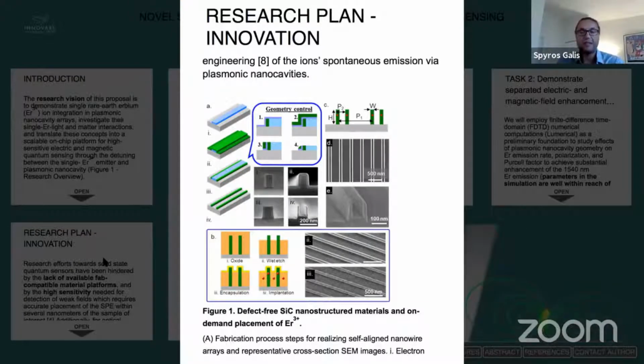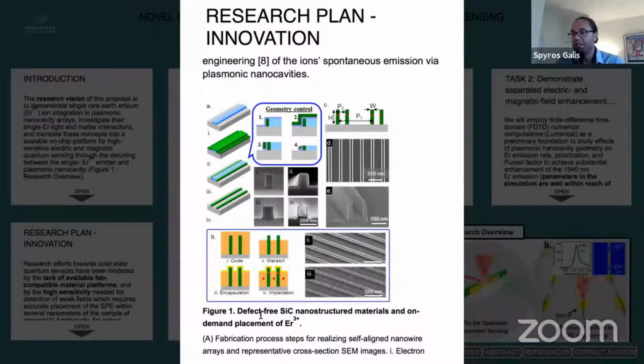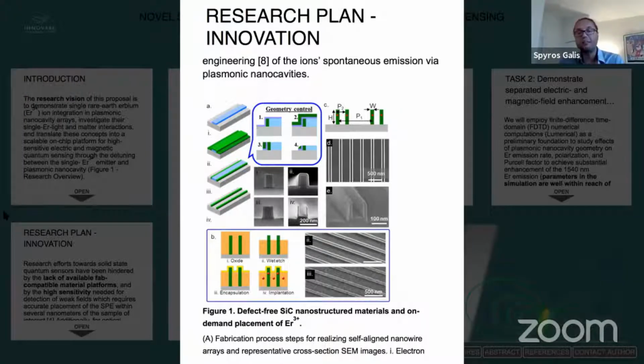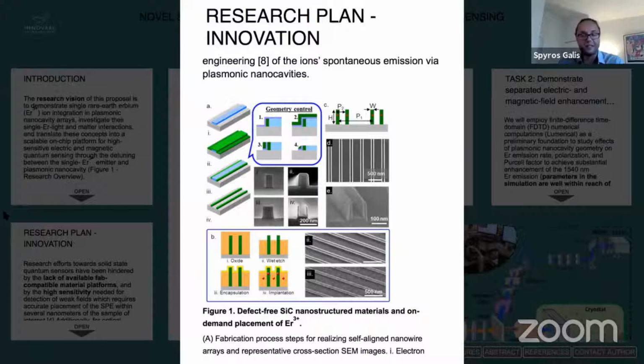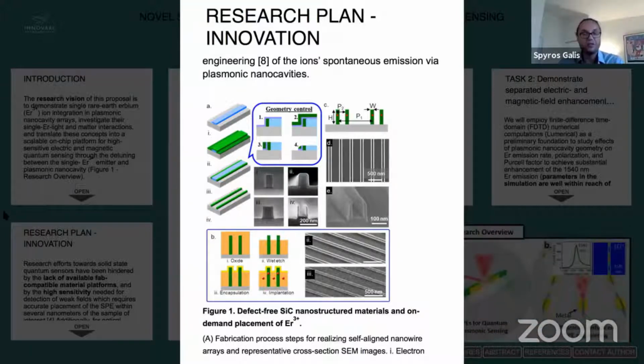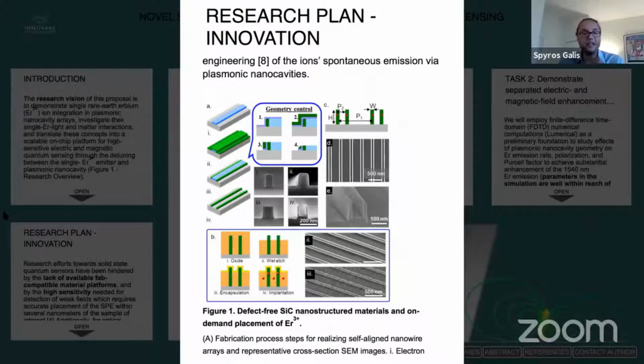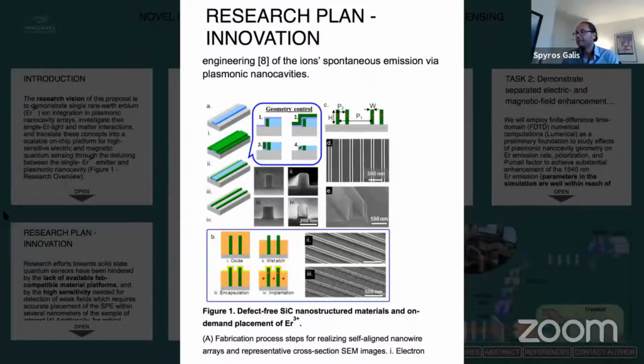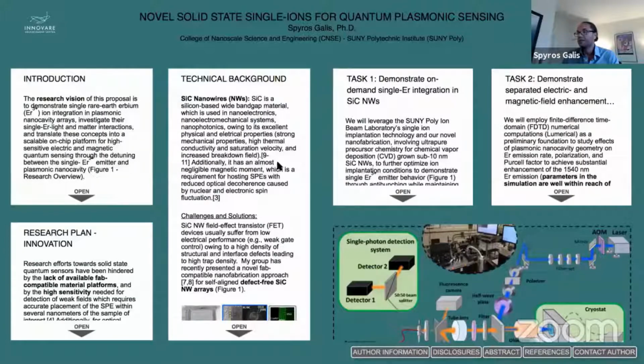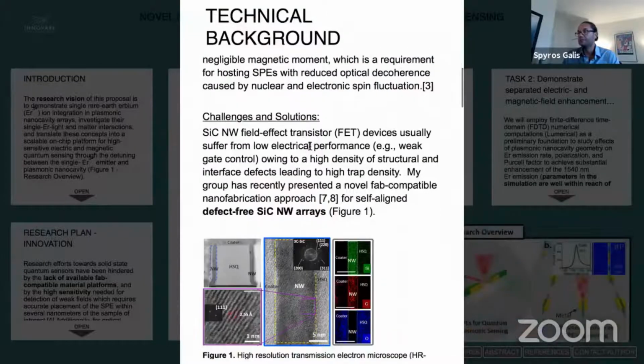So let me address this by saying we have recently demonstrated in nanophotonics state-of-the-art high accuracy placement, less than 10 nanometer, of erbium ions in defect-free silicon carbide nanowires. These two demonstrations are key building blocks towards the development of the next generation of scalable on-chip quantum devices, which will require the proper engineering of the single emitters, and also will require the minimization, if not reduction, of defect densities in these devices. This becomes even more important.